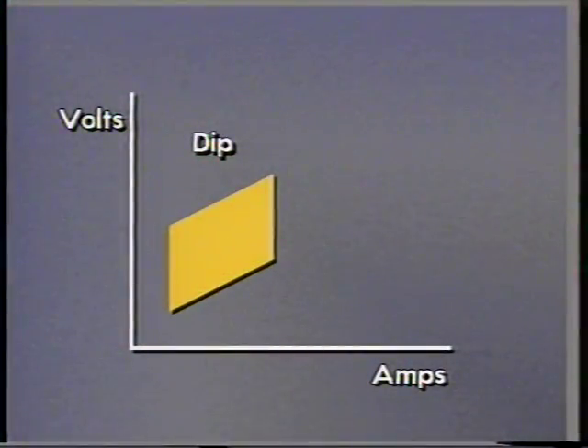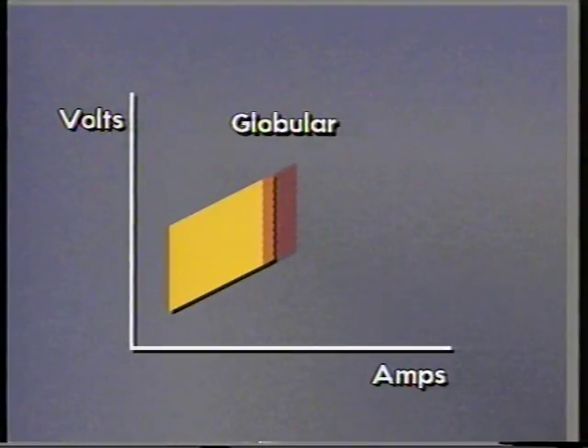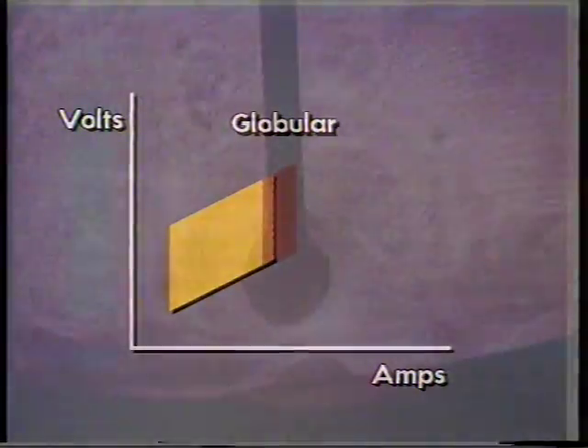Globular transfer occurs at slightly higher currents than dip transfer and can be found when using carbon steel wires with carbon dioxide shielding gas. Large droplets are formed at the end of the wire, which are detached by gravity. Transfer is irregular and unstable, giving rise to large amounts of spatter.